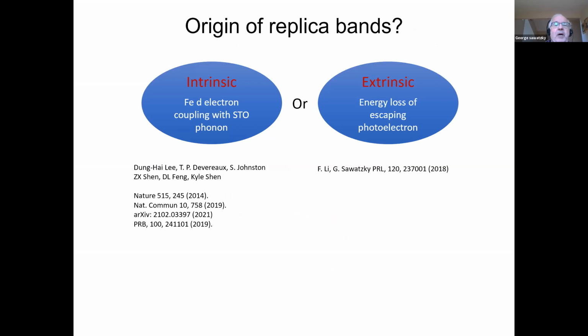There's two ways of getting these replica bands. One way is that there is an electron phonon coupling of the d electrons, which are the electrons basically at the Fermi energy of iron, coupling with the phonons of strontium titanate. And it would have to couple with these Fuchs-Kliewer type phonons, and I'll describe them in a second. Those are at about 100 millielectron volts. They're the longitudinal optical phonons in the bulk, and the transverse optical phonon corresponding to that longitudinal optical phonon is your soft mode. It's at 10 or 15 millielectron volts.